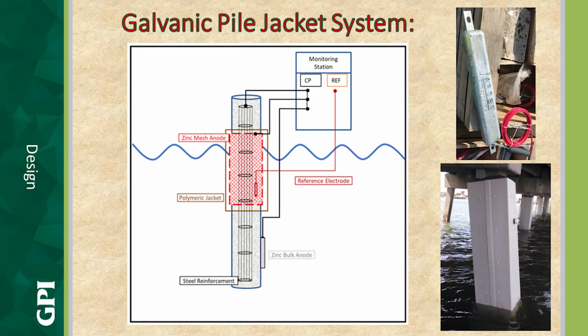Below the waterline, we install bulk zinc anodes. By embedding a reference electrode in the grout and wiring the components into an accessible junction box, we can monitor the performance of the system by measuring the potential between the grout and the steel reinforcement.